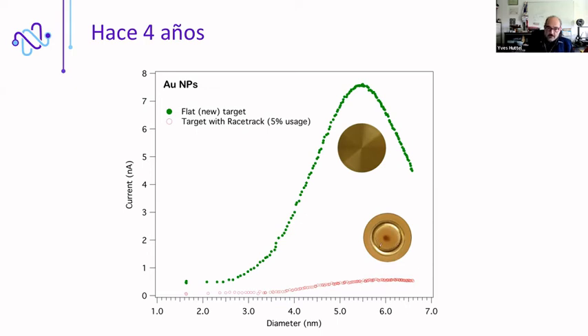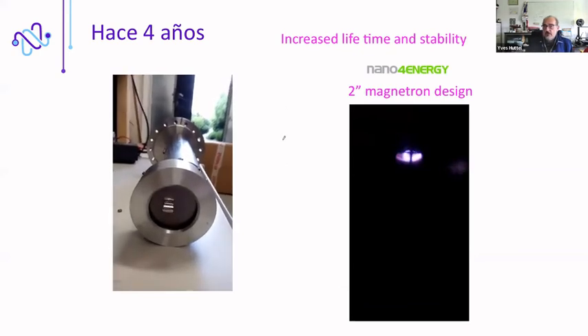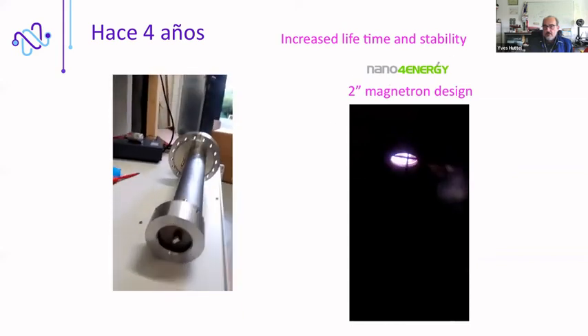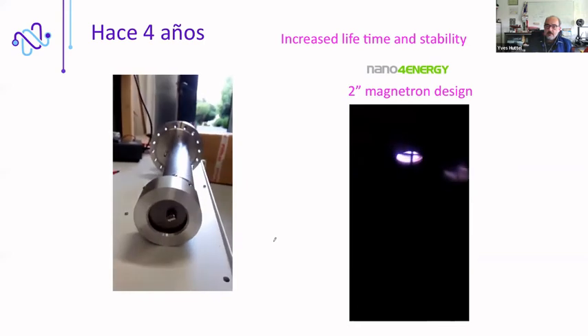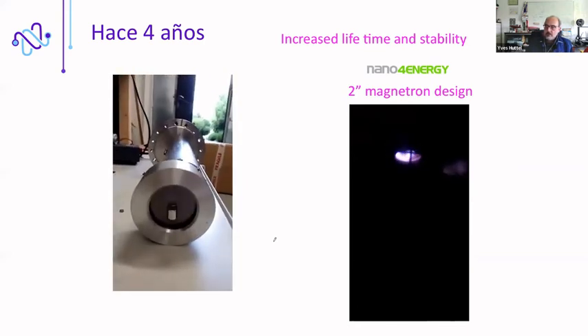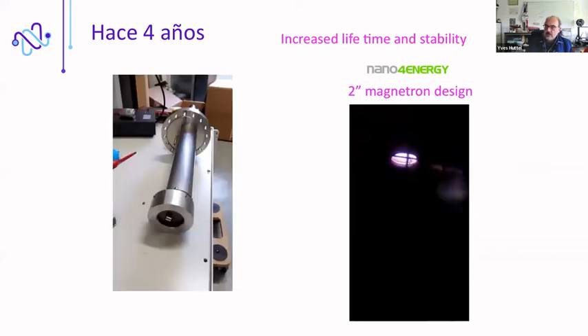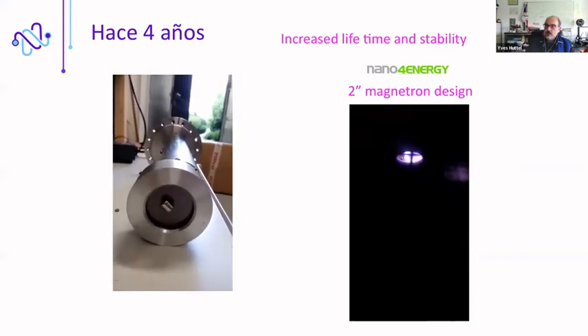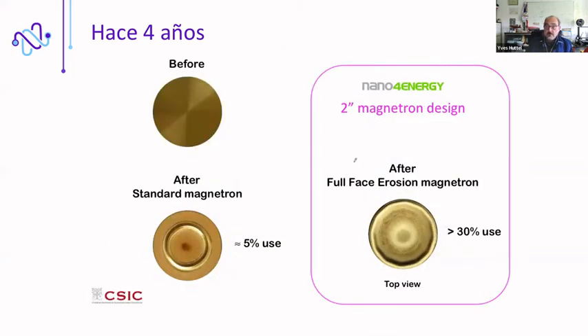Once you have this problem, you have to open again and replace the target in order to continue fabricating the nanoparticles. So what we have done is to develop a new magnetron with the company Nano4Energy, where instead of having magnets that are fixed in a position, the magnets can rotate in such a way that the plasma is distributed over the whole target. So we can erode the target more uniformly. The result is that instead of using only 5% of the mass of your target, you can use more than 30% of it, which is very convenient, first if you are using gold, which is quite expensive, but also because you don't have to open your system and replace the target. And secondly, you have a stable production of the nanoparticles.